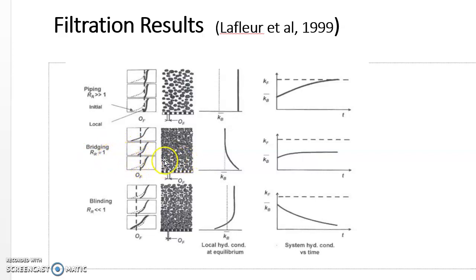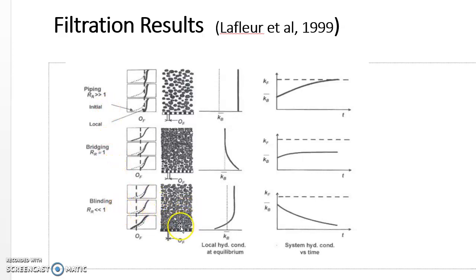Bridging is a successful case where fine particles in some upstream area are suppressed by a separate filtration structure. The drainage function is also satisfied, with hydraulic conductivity slightly increased and close to the filter media but remaining suppressed in between the base soil and filter media. Blinding is the opposite case of piping: all fine particles become trapped at the interface of the filter media. That accumulation reduces the void ratio near the interface, and consequently the drainage function deteriorates continuously as testing time progresses. The filter phase can classify these three cases: piping and blinding as failure cases, and bridging as the success case.